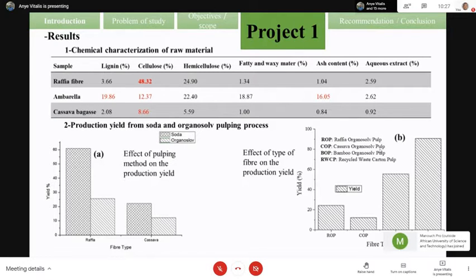So now we study the impact of the pulping process on the type of fiber, using raffia fiber and cassava fiber. We realize that with soda pulping and organosolv pulping, organosolv pulping gives fiber with a lower production yield compared to soda. But by doing characterization, we realize that there was a significant removal of the amorphous part using organosolv compared to soda pulping.